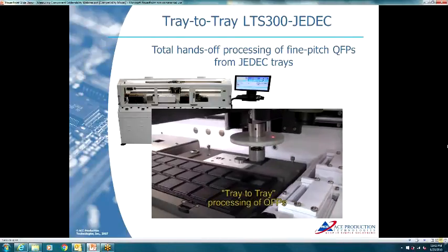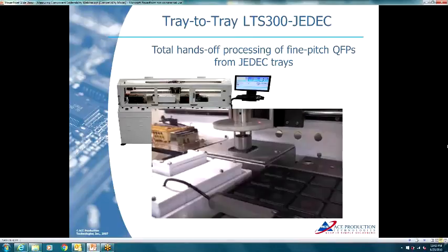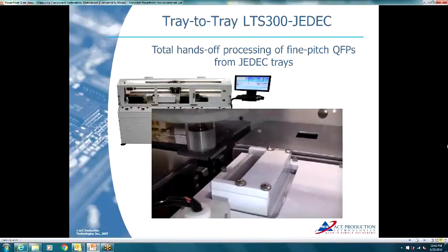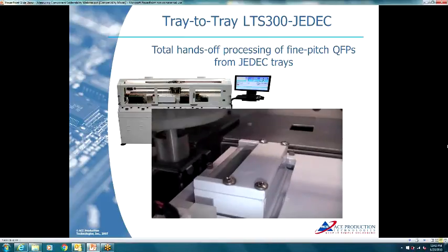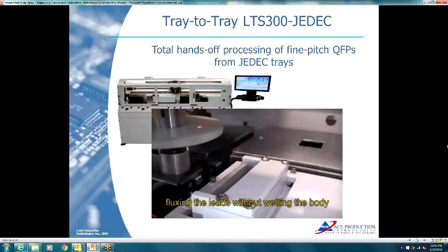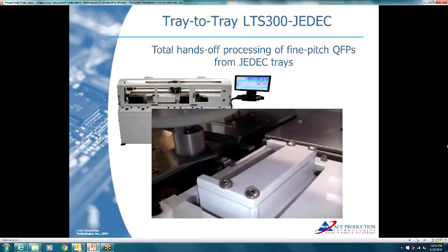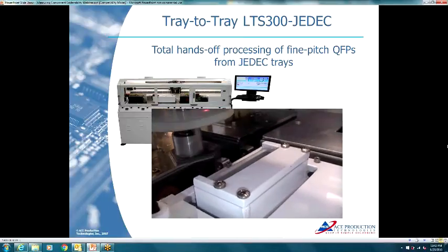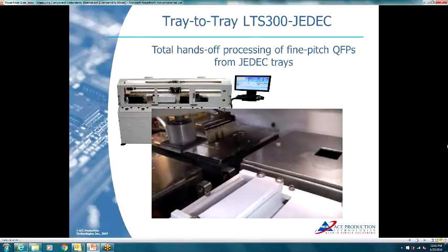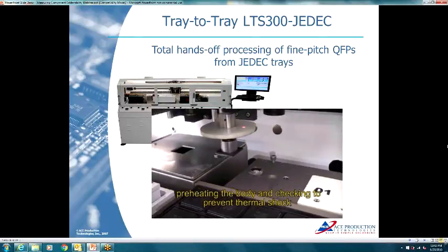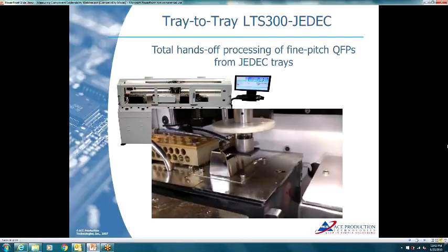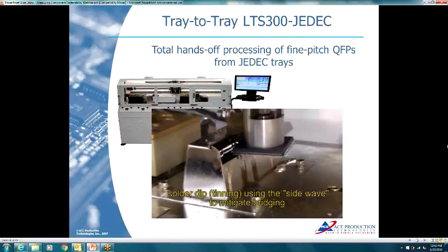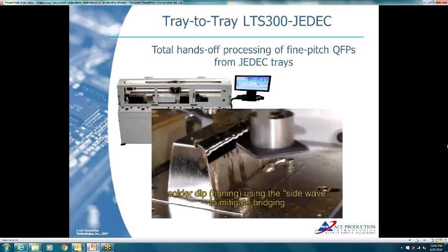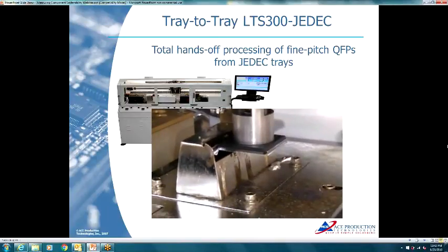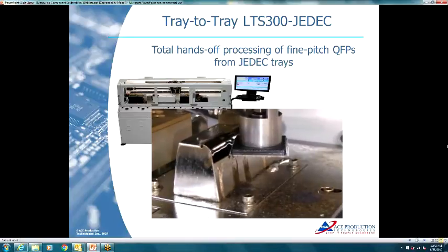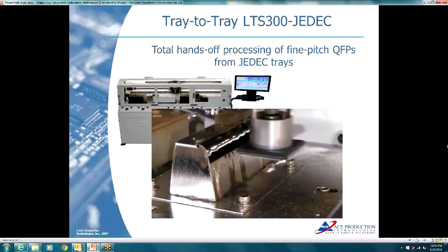Here's an example of retinning fine pitch QFPs. They're taken out of a JEDEC tray, and they have to be fluxed and preheated. You notice you have to flux each one of the sides individually without touching the flux to the plastic body, so you have to rotate and articulate it. The part is then heated with convection reflow, and again, you have to solder dip each side and pull away on an angle to minimize bridging. You'll see that it's a very delicate operation. We can go down to 12 mil pitch.